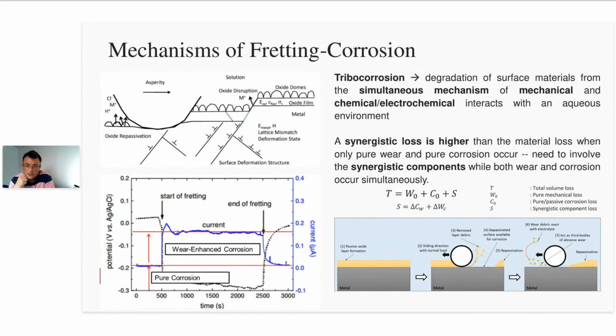But when we have these processes occurring within tribological contacts, what we have is this constant abrasion and removal of an oxide film, which we can term tribocorrosion. And ultimately, fretting corrosion is a subset of this tribocorrosion mechanism, where we're dealing with these combined mechanical and chemical interactions within a fretting contact. And ultimately, we can describe the material loss from that interface as a combination of both wear and corrosion.